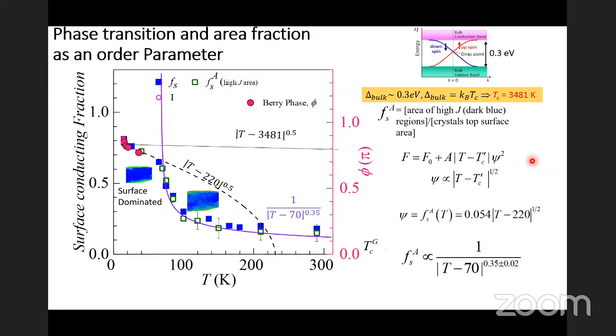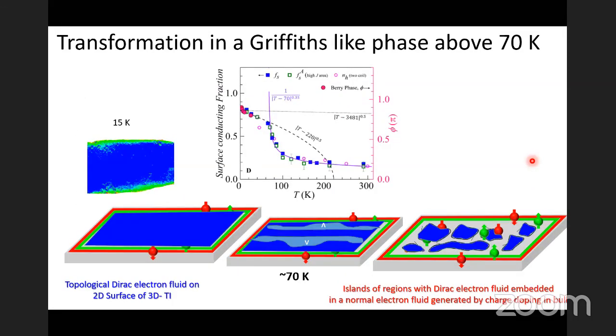So what we suggest is that there is a disorder induced Griffiths phase like transformation at 70 Kelvin. Below 70 Kelvin, you have uniform Dirac like surface electrons present on the surface. These are 2D surface electrons. At 70 Kelvin, you are breaking up the region into these patches where the light blue regions contain normal electrons generated by the selenium vacancies in the bulk. And so you have two different fractions of electrons. One fraction are the Dirac surface electrons. The other fraction are the electrons generated in the bulk.